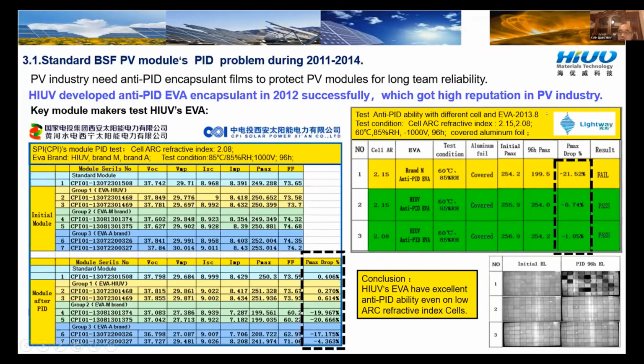It's also another module maker in Hebei province. They tested with a foreign brand, covered with aluminum foil for testing. Okay, this one only dropped 20%. But look at this cell. Their AR reflection is 2.15. But what they tested through our product is 2.15 and 2.08. This one is very weak for anti-PID from the cell level. But we still passed. So that is the EL pictures of these three tests. So HIUV's EVA has excellent anti-PID ability, even on low ARC refractive index cells.